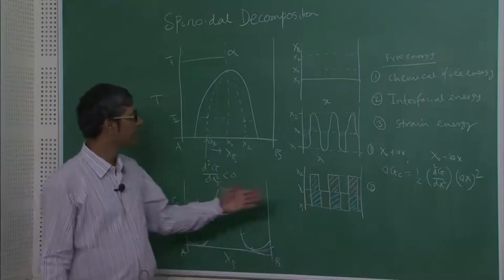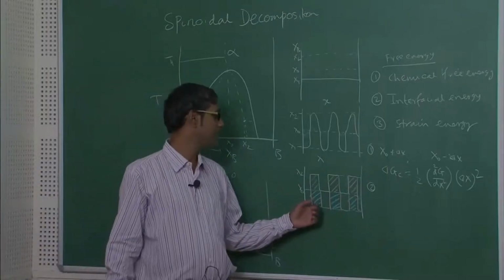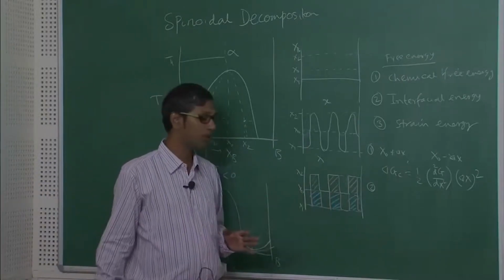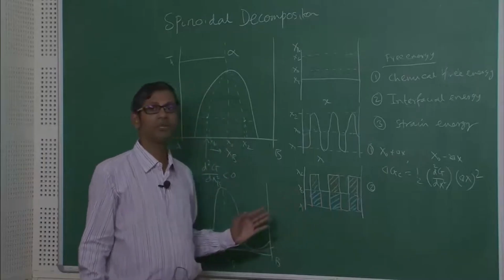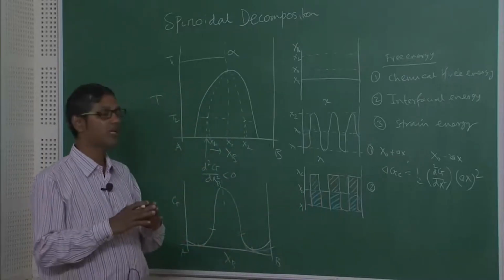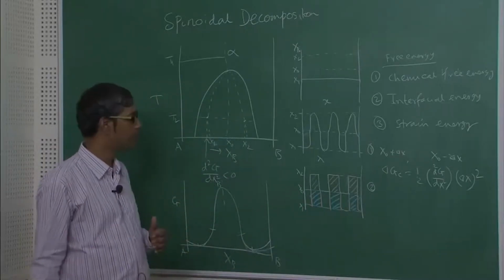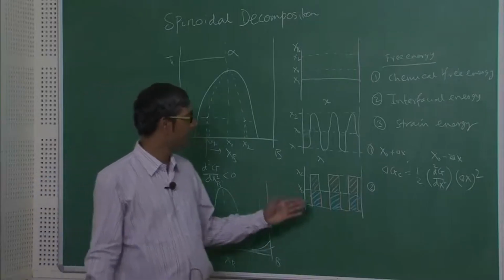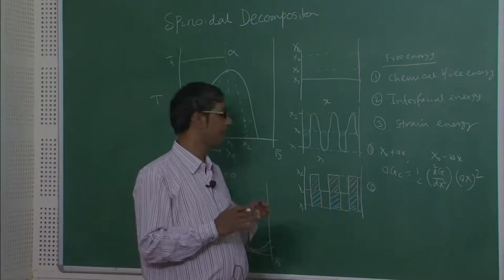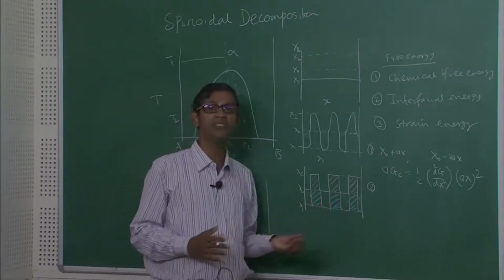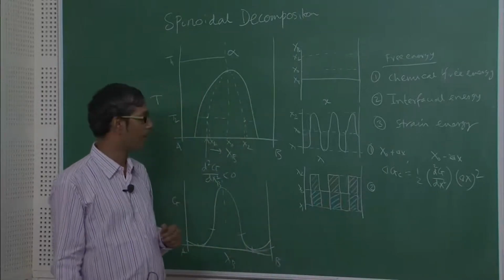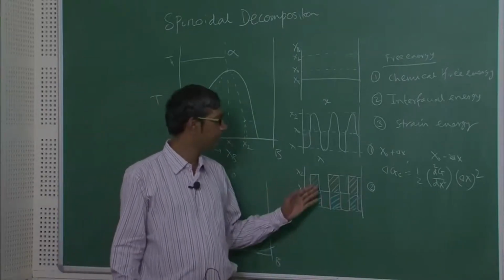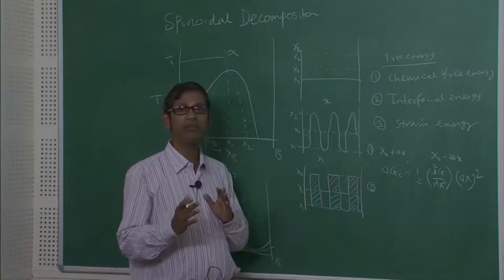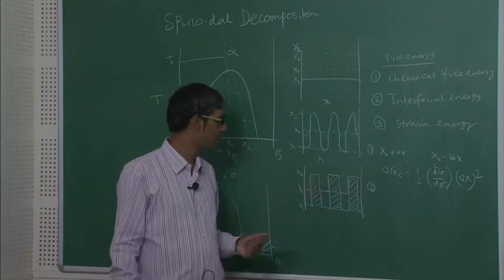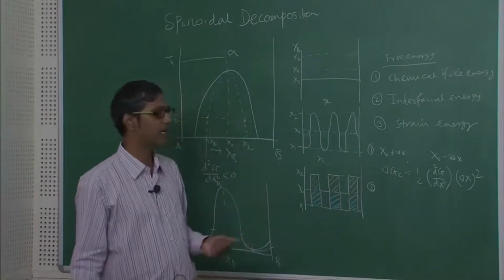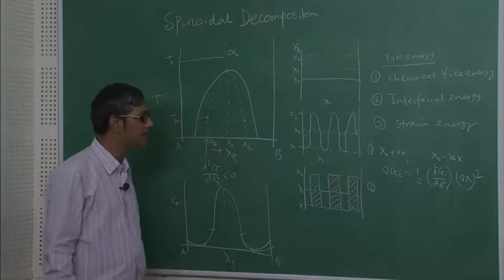Why? Because the system does not like to stay as dissimilar atoms. This is different from the random solutions where the system will have more number of dissimilar bonds than the similar bonds. Here the system will like to stay in such a way that clusters of A rich and B rich atoms are present in the alloy. So, whenever there is an interface between A and B rich, there will be dissimilar bonds, and dissimilar bonds will lead to interfacial energy. How to calculate that in this one?